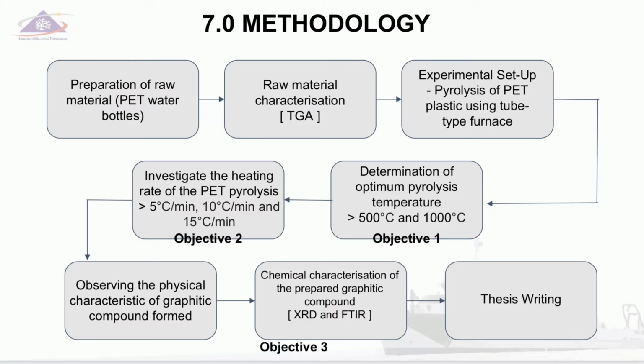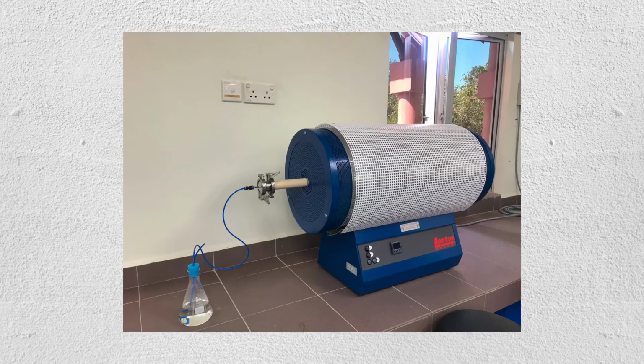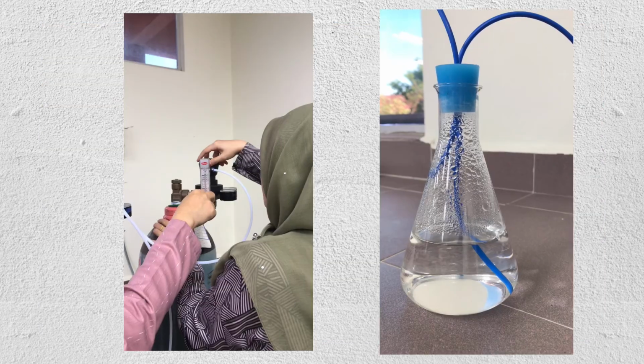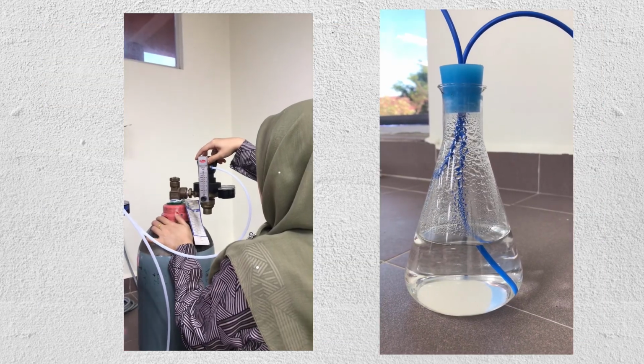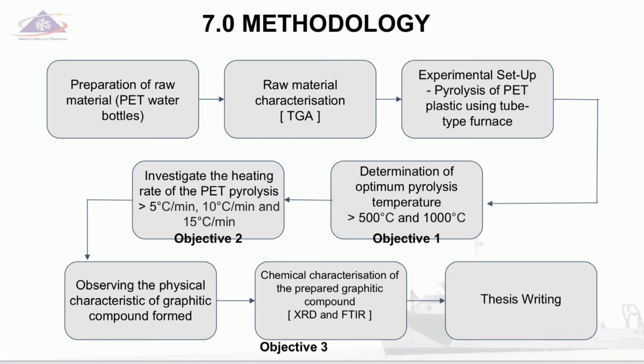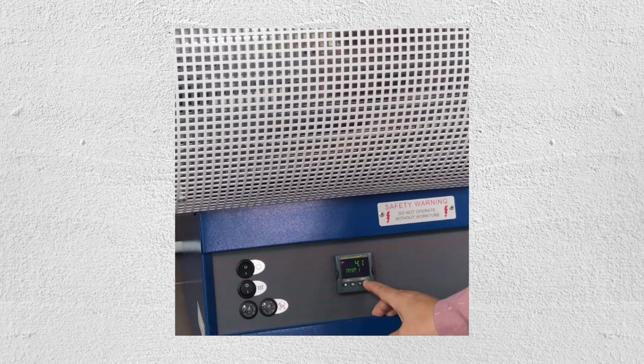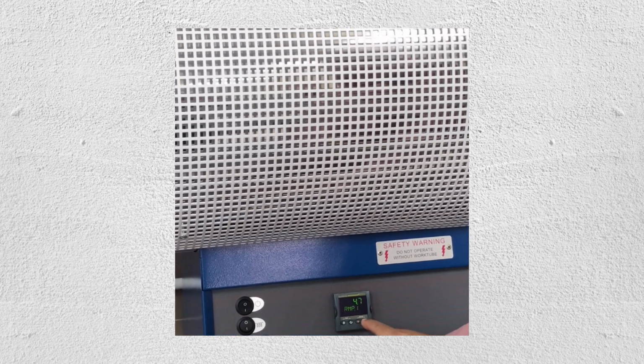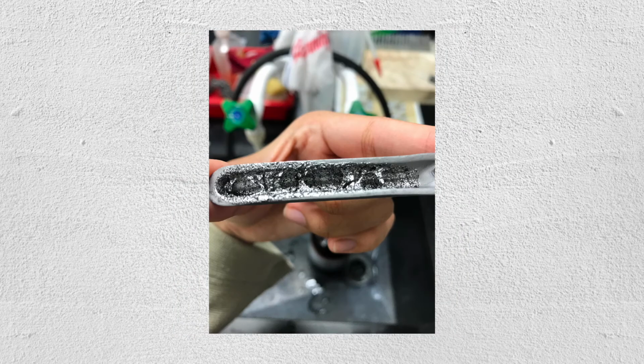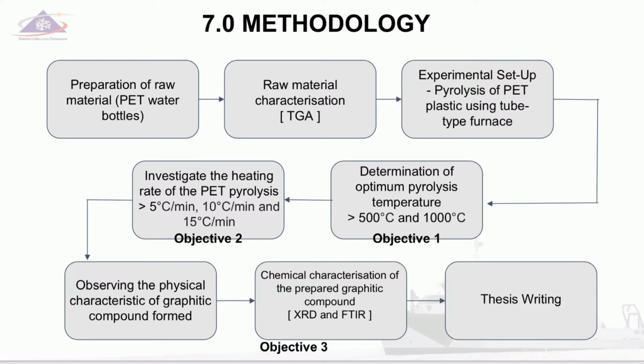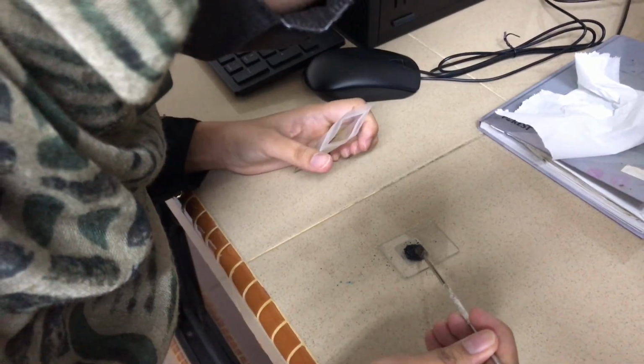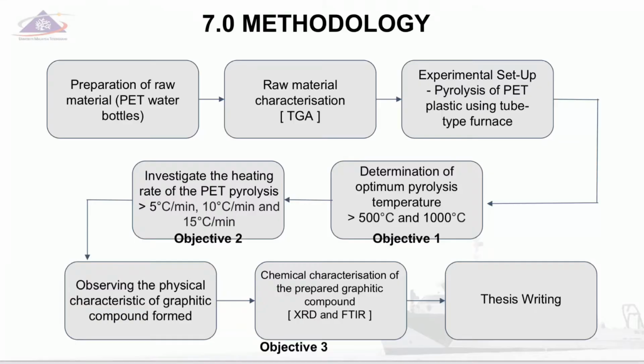Methodology: PET bottles were cut finely into flake shape, and their thermal behavior was then analysed by TGA. The prepared samples were pyrolyzed in a tube-type furnace. To create an inert environment, nitrogen gas was circulated through the furnace, and each set of experiment has a holding time of 1 hour. The PET flakes were pyrolyzed in 6 different sets, where the lowest temperature chosen is 500 degrees Celsius and the highest 1000 degrees Celsius, with 3 different heating rates studied of 5, 10, and 15 degrees Celsius per minute. The samples produced are analysed and characterized by XRD and FTIR to observe the influence of the pyrolysis process on the formation of the graphitic structures.